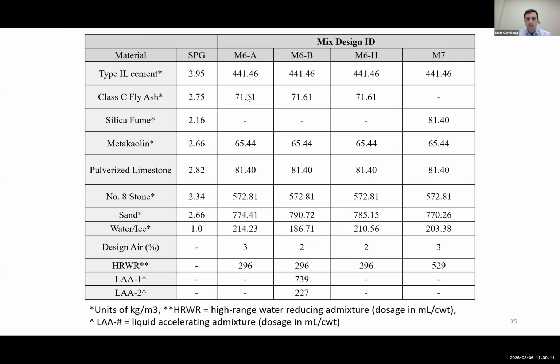And here are the mix designs. I won't go through it all, but we basically had 2 variations of the M6 one with different dosages of an accelerating admixture. We also had a third one that was applying heat to help further expedite the flexural strength gain. And then the last one was using silica fume as a replacement for Class C fly ash.